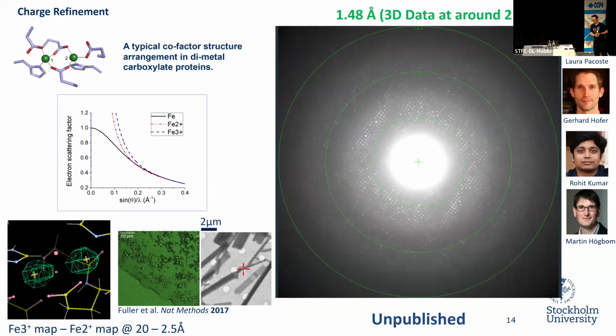So there are 3 major problems. First, it's very fundamental: how much electron dose can we give to the crystal before the charge gets reduced, which is, I think, a very important question. And I think the physics behind electron diffraction and X-ray diffraction is slightly different, and with all these secondary electrons generated by electrons, because the crystal is so small, maybe they escape much more easily and cause less reduction of the ions. So that's something we are hoping, and we're working on electron energy loss spectroscopy, trying to figure out what the critical dose is that is going to cause the reduction of the charge.